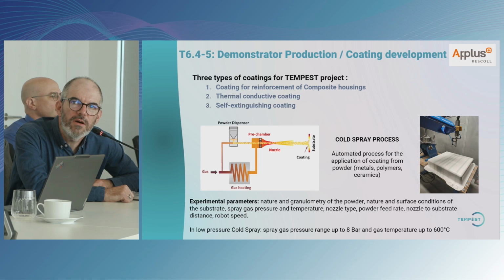The work from RESCOLL was also focused on other coatings with different functions. In tasks 6.4 and 6.5, we used the other technologies we've developed to give different functions to the pack housing. So my colleagues developed a set of 3 different coatings with cold spray technology. The first one was used for mechanical reinforcement of the composite housing, for instance, if there is an abrasion with a stone or something. Then a thermal conductive coating, as shown previously by University of Bath, to improve the efficiency of cooling plates and heat sinks, and then a self-extinguishing coating that was used internally in the housing to prevent any fire spread from the cells to the exterior.